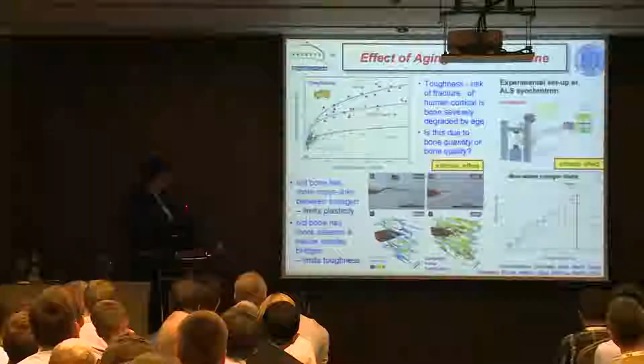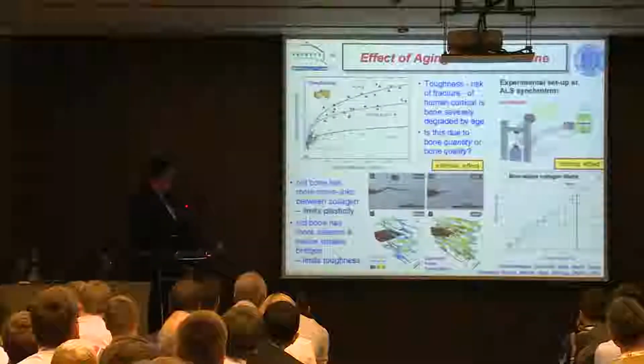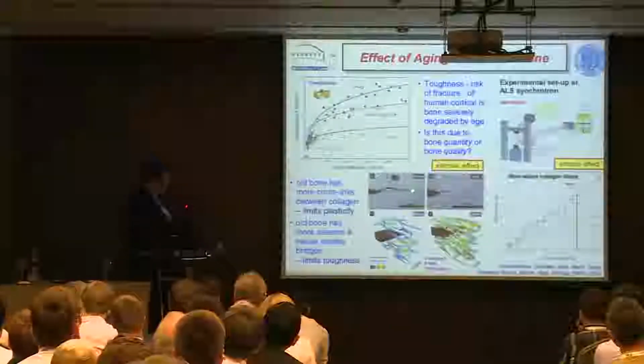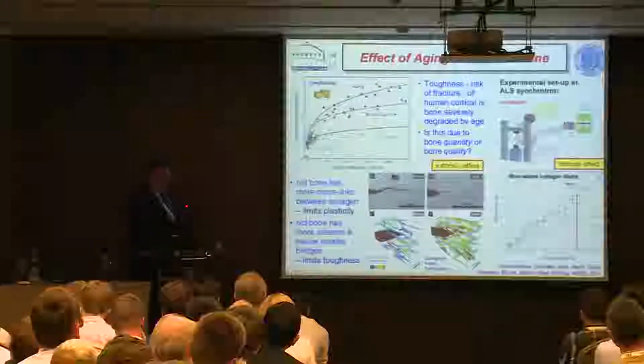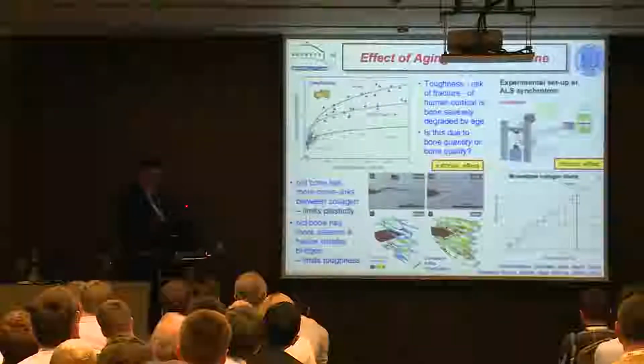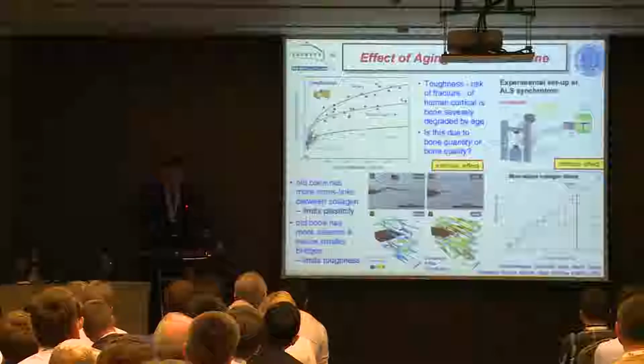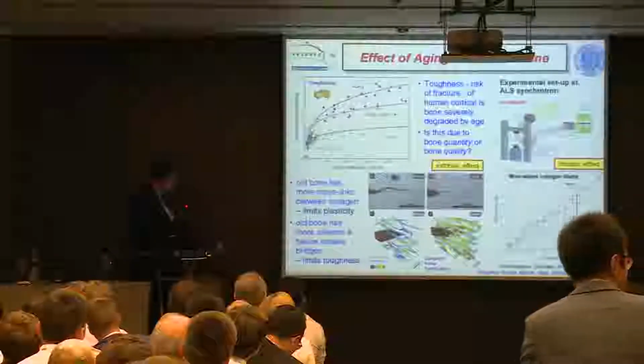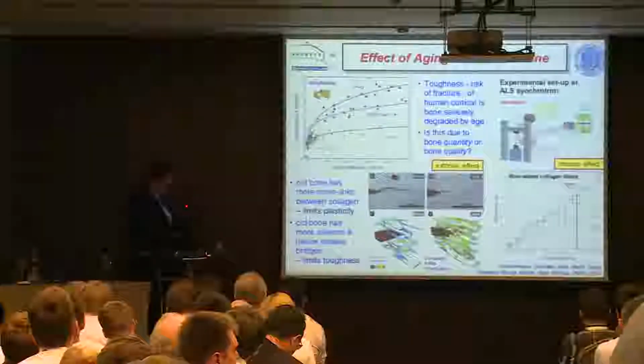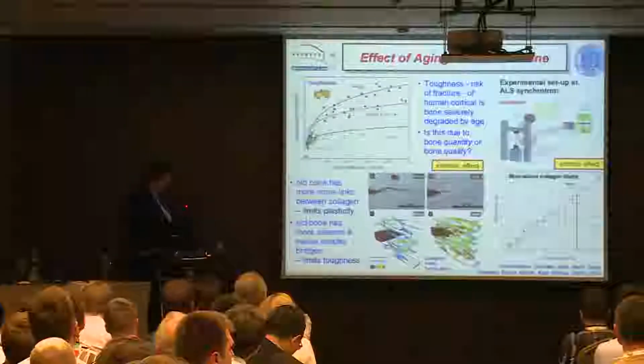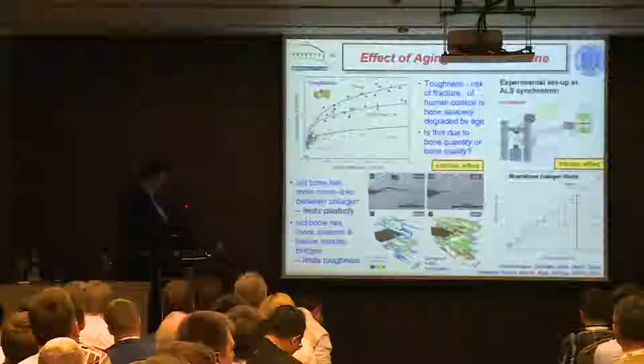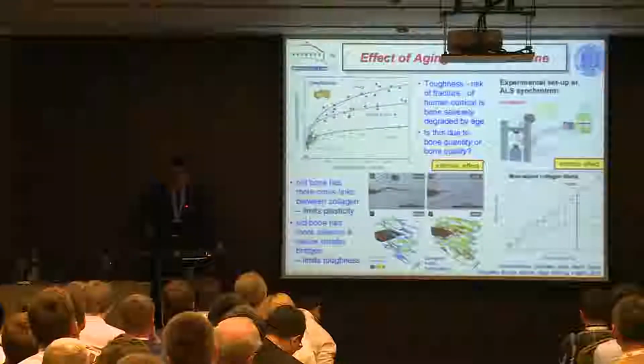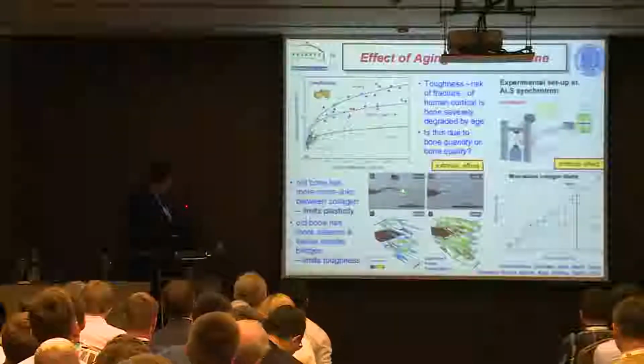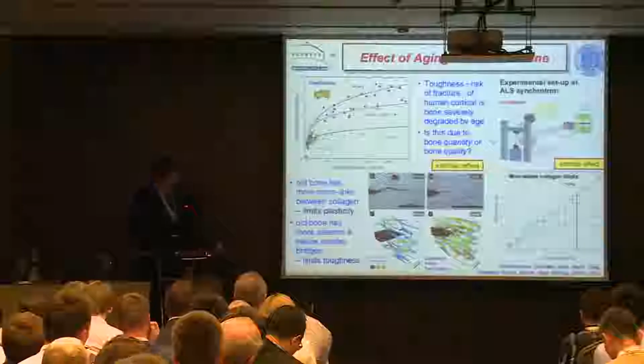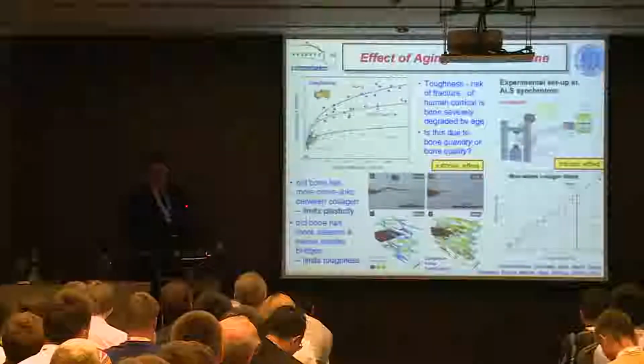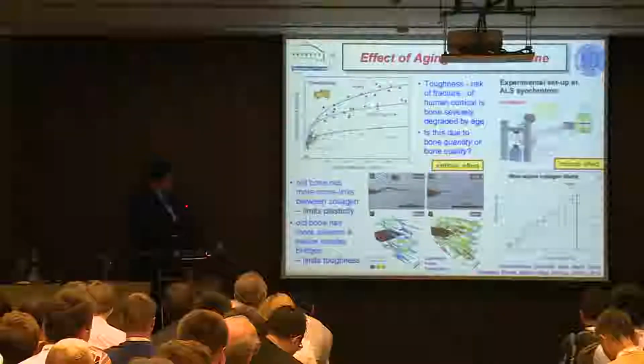So why is that? Well, just quickly, you can again subdivide this into intrinsic and extrinsic. Extrinsically, you see these little uncracked ligaments, these little uncracked regions that act as bridges. Their spacing is typically the spacing between the osteons, because that's where the microcracks will form in those mineralized boundaries. But if you look at a piece of young bone versus a piece of old bone, this is tomography, you see these blue and green columns are the osteons, and what you can see is there's a dramatic increase in the density of osteons as you get older, particularly if you have excessive remodeling. And since these little bridges are a function of the spacing of the osteons, what happens as you get older is this bridging effect is much less effective. So there's a deterioration in the crack growth toughness.